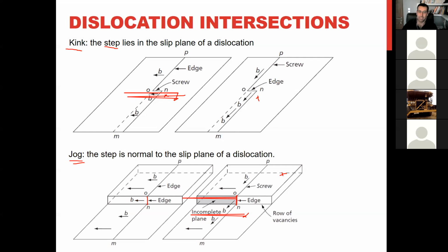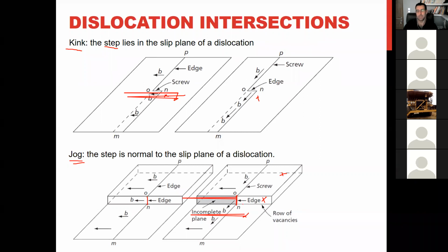But in this condition, the Burgers vector of this edge is in this direction, and the slip plane is this, so it is perpendicular to the slip plane. So this part of the dislocation, this jog, is sessile. It means this part of the dislocation cannot move. Sometimes when dislocations intersect, they can make sessile jogs, and part of the dislocation is locked. When they become locked, the movement of dislocation is difficult.